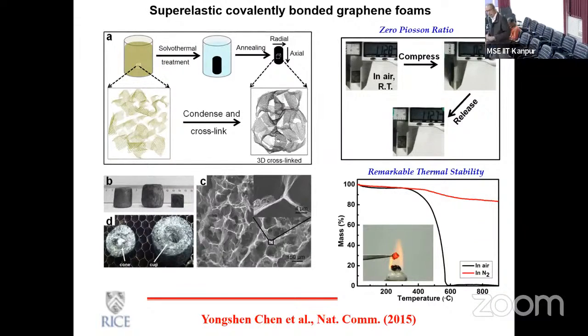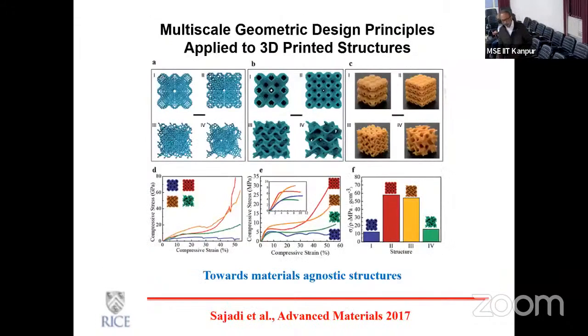And when you can do that, you get materials that are really remarkable, with a huge range of thermoelasticity. The graphene foams that we were able to create were extremely elastic at cryogenic temperatures, as well as at 1,000 degrees Celsius. So again, the power of nanotechnology and nanomaterials is that if you can design and build and engineer these materials in the right way, you have a remarkable range of properties that otherwise cannot be achieved.